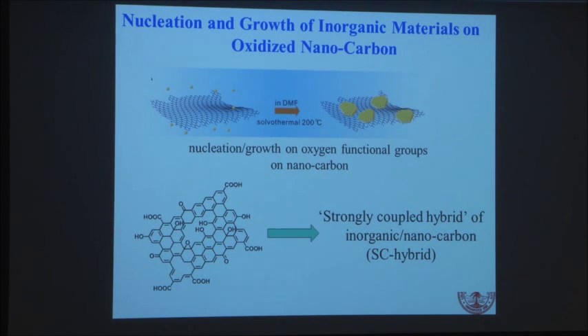Okay, so the way that works is actually we have a nucleation and growth process. So these metal ions would bond with this negative charged oxygen, okay, and stick. So that's the first step. It's a nucleation step. And then you can control the conditions so that the nucleation sites grow a particle for you. So this way you actually have very strong bonding between the particle and the carbon. So we call it a strongly coupled hybrid.